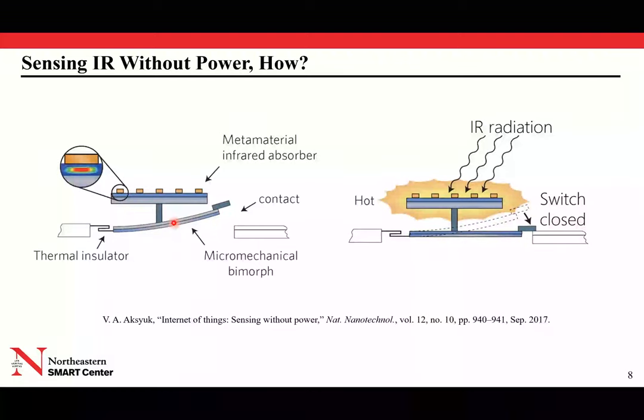Now, on the top surface of this cantilever, we're also integrating this metamaterial infrared absorber. I'll talk a little bit more about that. But basically, the idea is that we want a very thin structure, on the order of a few hundred nanometers, that can very efficiently absorb radiation in the mid or long infrared range. So if we expose this device to infrared radiation that matches the absorption wavelength defined lithographically in this absorber, the energy will be absorbed by the device, and the temperature of this micromechanical cantilever will increase. That will cause a downward bending of the cantilever, and therefore a vertical displacement of this contact tip.